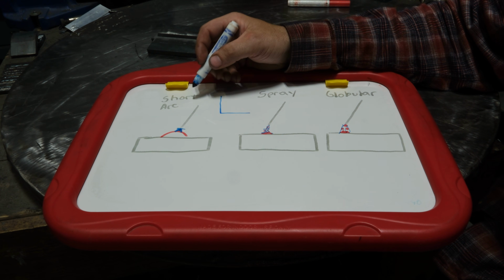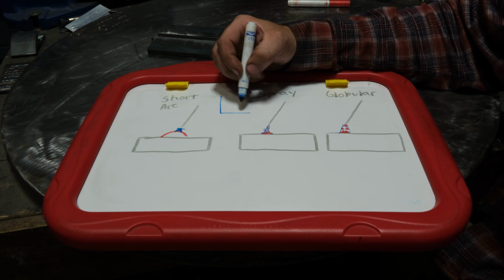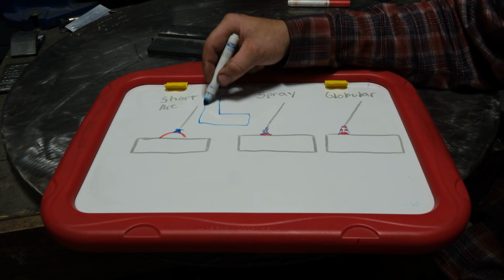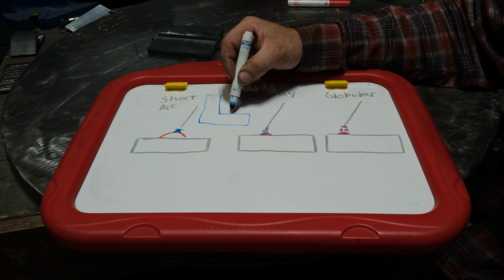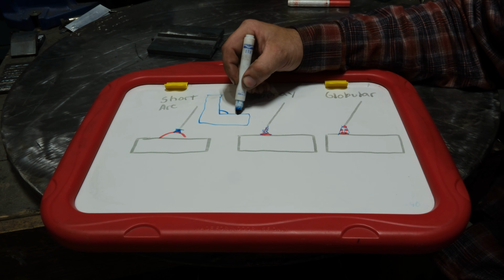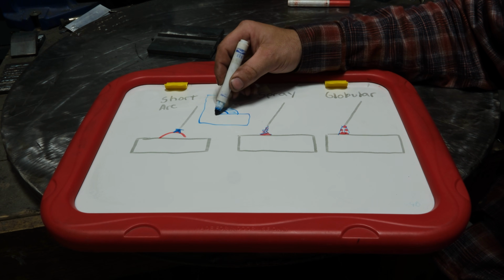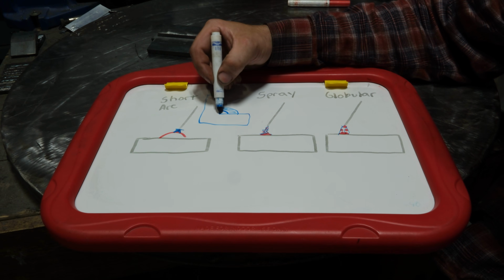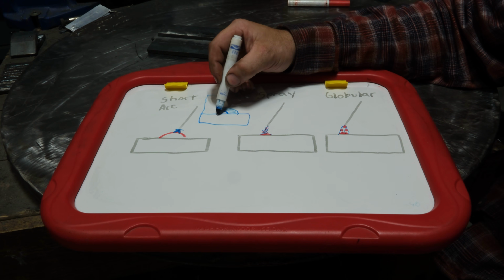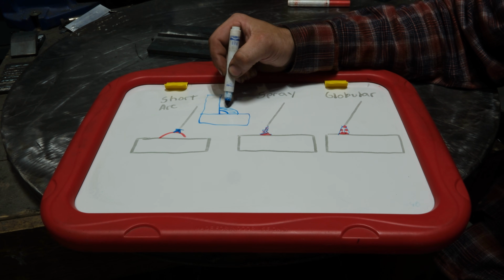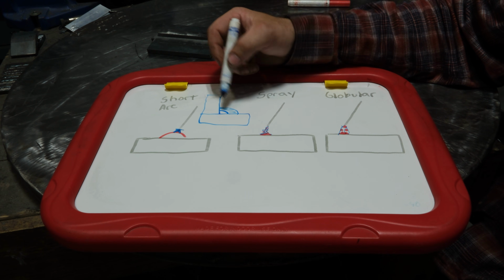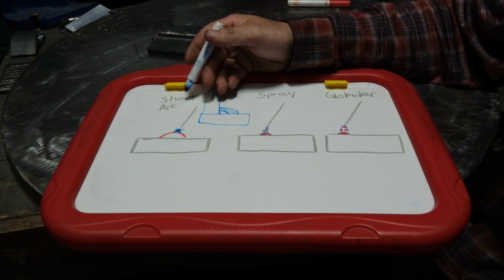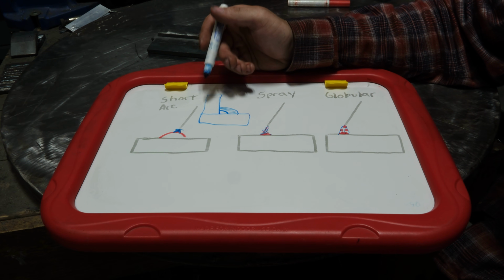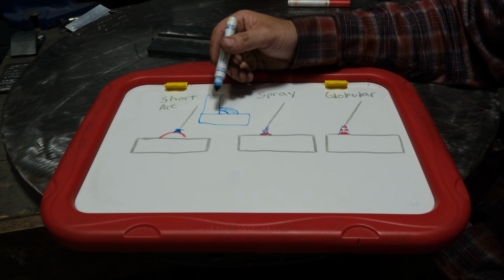Worst case scenario with the short arc process, if you were to try and weld, say, 1-inch thick steel, what will end up happening is the weld will bridge over the root completely. This is your weld, and it will not fuse anything down here in the root. I'll draw a little. It will not fuse anything here, and this is a bit exaggerated, but you don't have any fusion, and that's very typical of that process, and there really isn't any magic on getting around that, unfortunately.